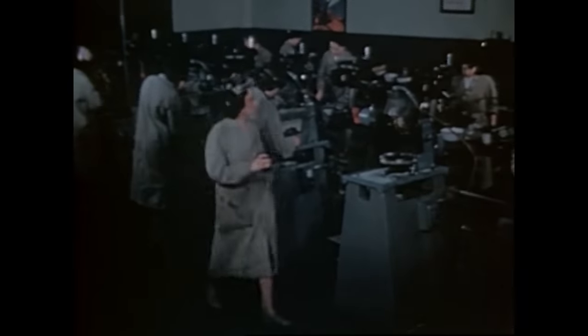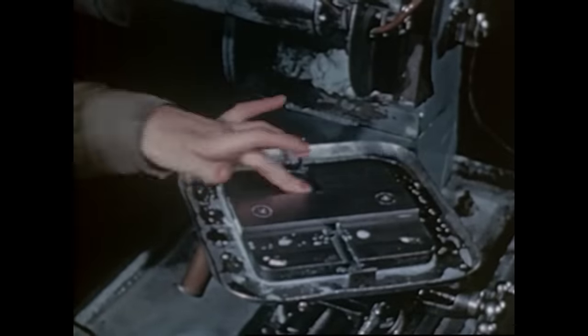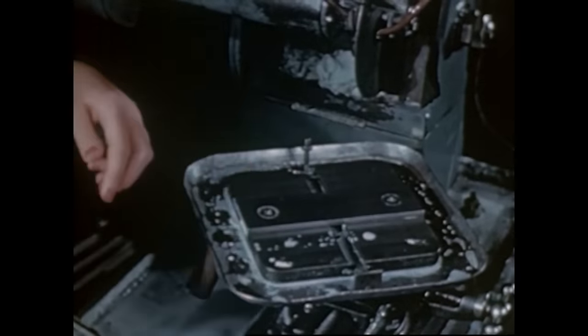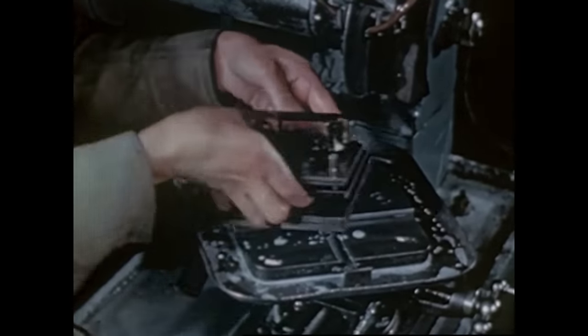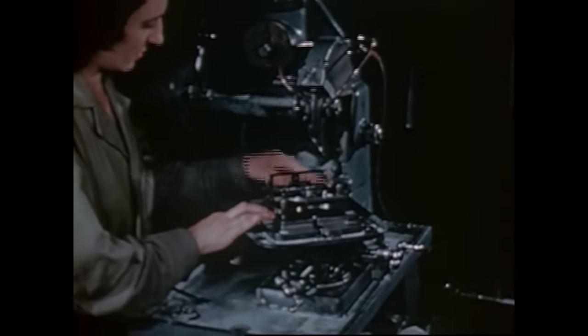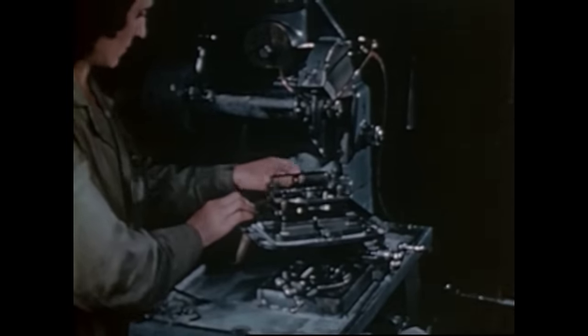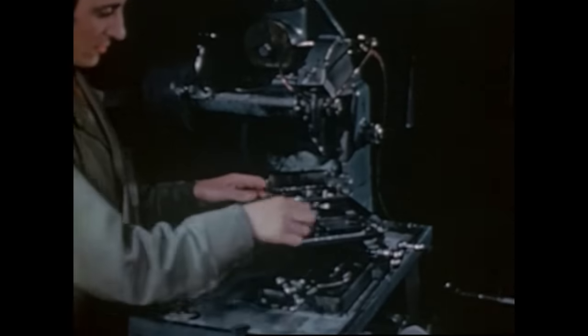In looking back, we have seen the mother crystal sawed into slabs, and one of these in turn into several bars. Wafers are next to be precisely cut from one of these bars on the basis of the electric, optic, and X-ray tests which we have just seen. On the bottom of the steel jig upon which the crystal is mounted is a groove that fits accurately into a runner on the saw table, ensuring that the quartz cut will be in accordance with the X-ray measurements. Vertical arrows have been drawn on the quartz in two previous operations so that the crystal would not get inverted.